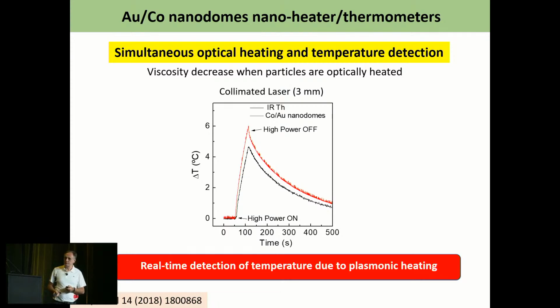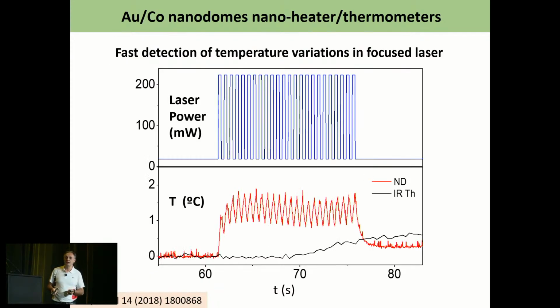And a nice advantage of this is that this approach using the nanodomes is much faster in response than the infrared thermometer. And here, what we did is to have laser pulses of a few seconds each, and you see that using the nanoparticles, we can nicely follow the pulses of the laser, while the infrared thermometer just feels the accumulated effect after a few seconds. So with the nanoparticles, we can really measure the local temperature of the liquid surrounding the nanoparticles.